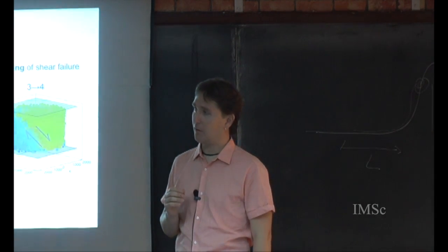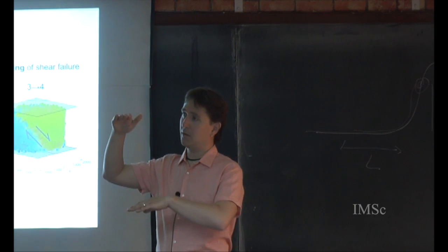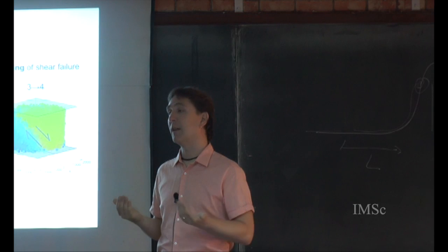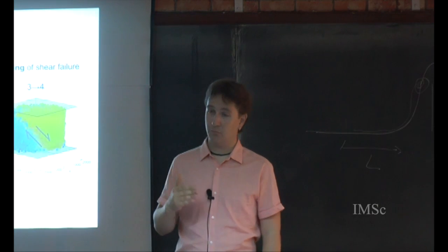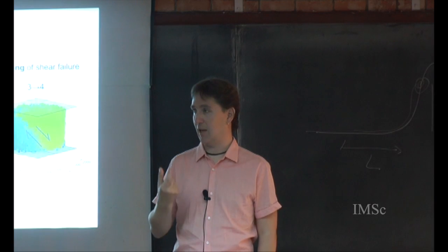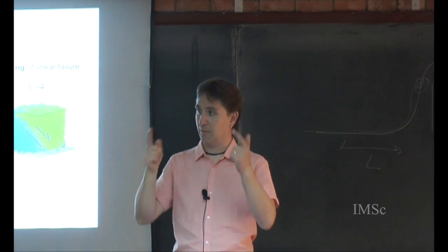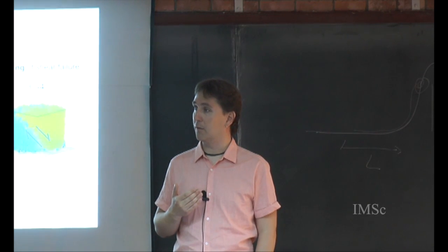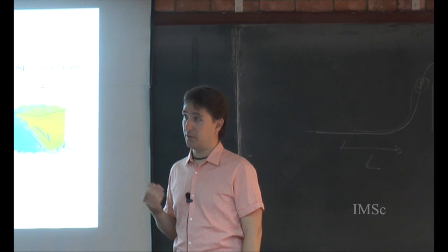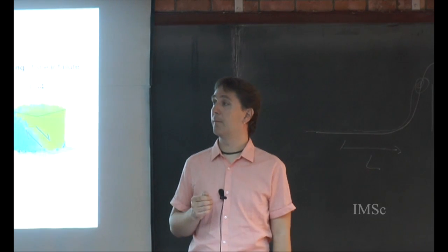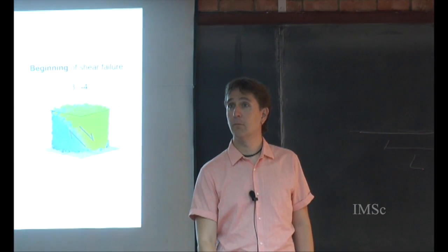I mean, if you look at a sandcastle, you can build a fairly tall sandcastle before you'll get a fundamental difference between the material at the top and the bottom. That's what we're sampling here. So there is a limit, which you can calculate back of the envelope based on the capillary pressure in the pendular rings and gravity. It's a few centimeters for our largest bead size. Of course, if you go beyond that, yes, you'd assume something will happen. But in that sense, it is homogeneous, as we've tested. Anything else? Okay, then let's continue.